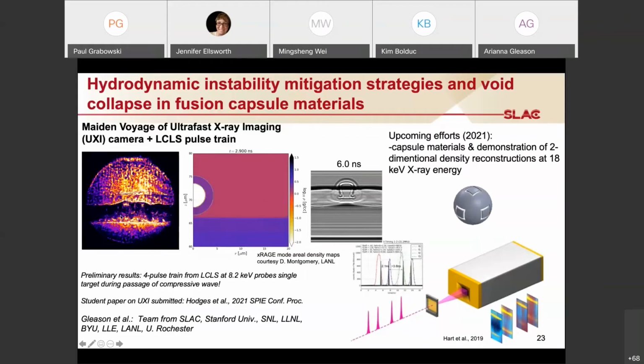These data were collected at 8.2 keV, so we're not able to penetrate through this ablation front. I think the good news is that we will leverage harder X-rays next time, 18 to 20 keV, and have more success. You can see there are maybe some gentle compressive waves that run out in front here, but we're not quite at the pressures that are important for ICF. But as far as looking at how the different components are working together, we're making progress.